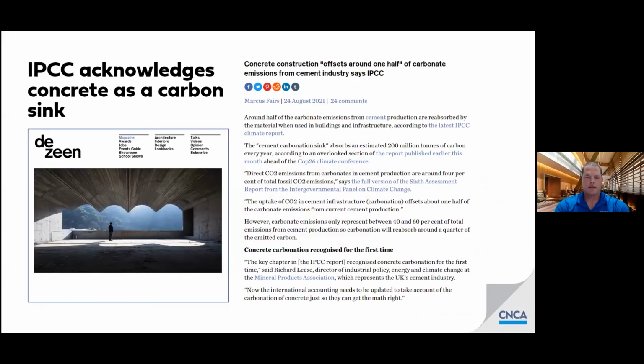Also want to draw your attention to some interesting information that came out of the COP26, which is the latest report from the Intergovernmental Panel on Climate Change. They have for the first time recognized that concrete is a carbon sink. When we put concrete in place over its lifetime, 40 to 60% of the CO2 that was emitted in the production of that concrete gets reabsorbed by the concrete itself. So this is fantastic news, something that didn't get as much press attention as maybe we might like, but want to make sure that you were aware of that.